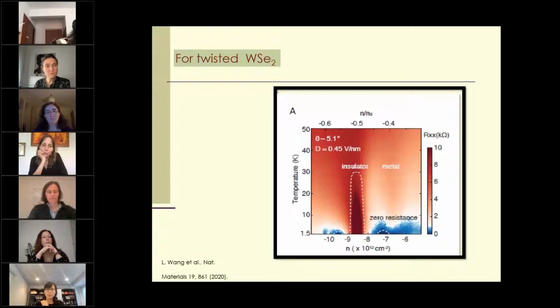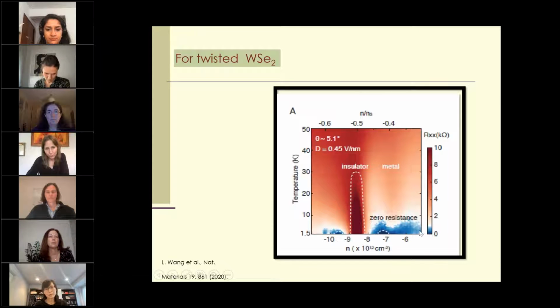And so the correlated phenomena that one sees in some of these, and I'm showing you here the experimental results from the group of Cory Dean and Abhay Pasupathy, where they have taken twisted bilayers of tungsten diselenide. And what you see is that if you take your Fermi level from the gap region and you're doping holes into the system, you go through states which have zero resistance, and then you go into regions which are insulating, and then again zero resistance states. So this seems very surprising because what you'd expect for a typical semiconductor would be a continuum of states.